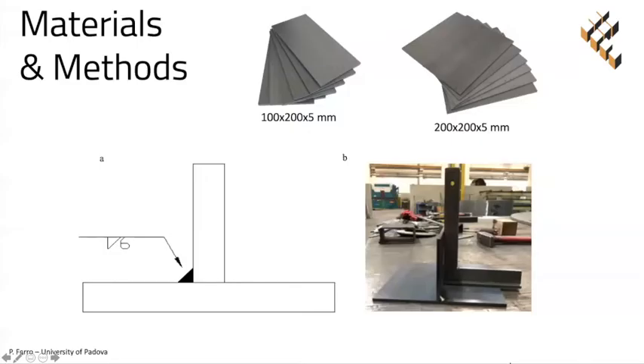Square groove T-joints were obtained by arc welding a 5 mm thick web on a 5 mm thick flange made out of S355 steel using a single pass on only one side, as shown in the figure on the left side. Before welding, the flange and the web were tack welded and perfectly positioned perpendicularly to each other using a square. See the figure on the right side.